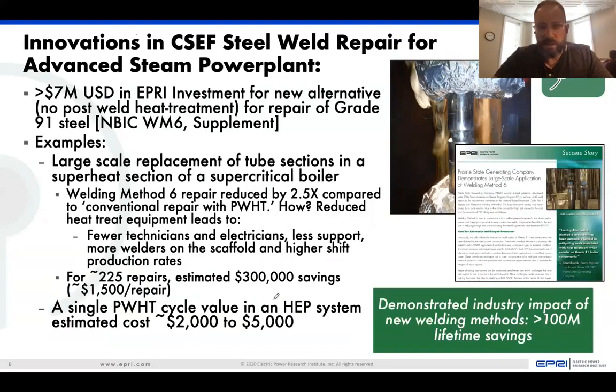We know of some limited instances even in India, but we know of instances around the globe, and in particular in the United States, we've documented over $10 million in savings a year for some members using these techniques that don't require post-weld heat treatment. It's risk mitigation for improper heat treatment as well as reducing the outage cycles. So as a tool in the toolbox, innovative repair strategies can save time and money and actually increase safety when done properly. And we have a lot of guidance in this area. And so this is an area that really should be on the forefront of the mind as you're operating supercritical power plants.